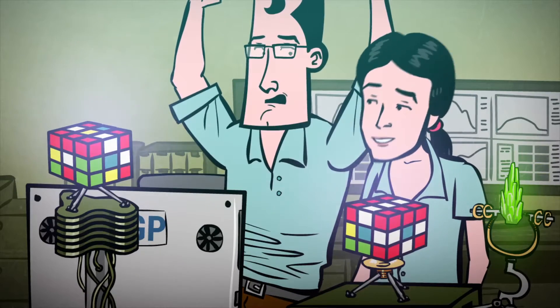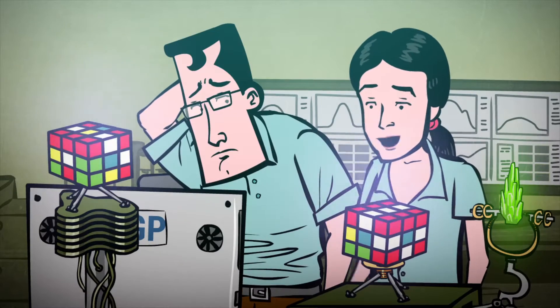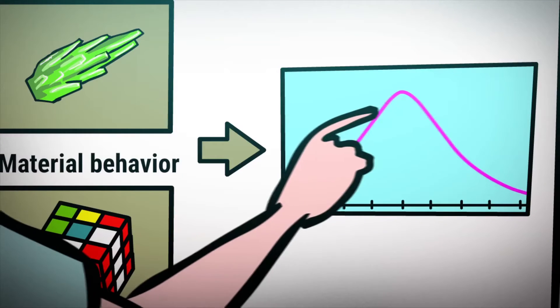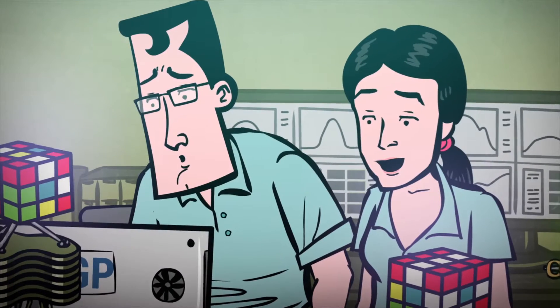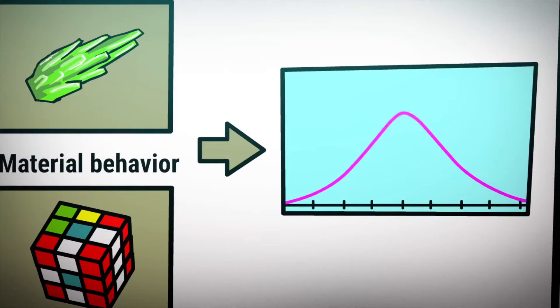What they found out is that this method is excellent in recognizing important, meaningful parameters. Peak location, area, and width of the peaks all arise directly from the parameters of the distribution function.